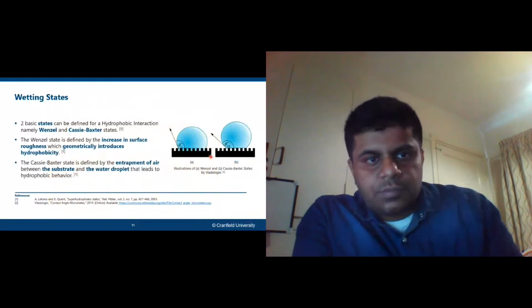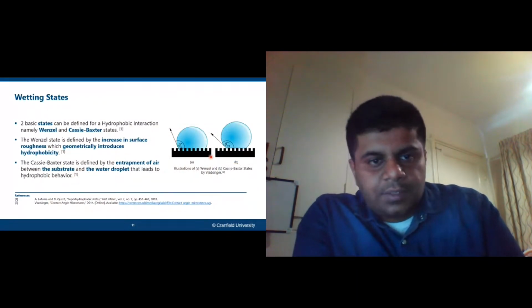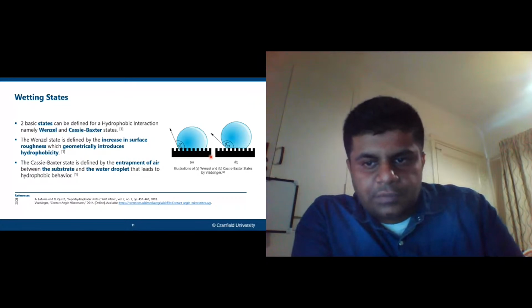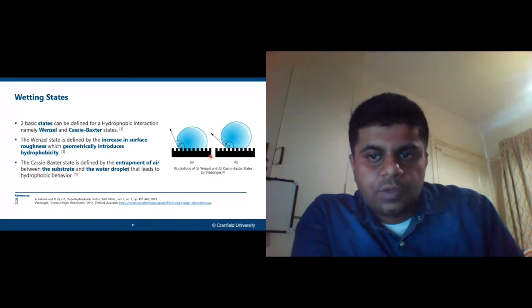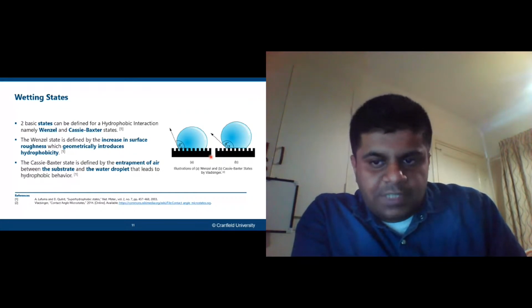So the two wetting states that we are discussing today are Wenzel and Cassie-Baxter. With regard to the Wenzel state, it's when the water droplet is fully in contact with the substrate surface down below. As you can see, the water droplet makes full intimate contact with the surface, and when you add more water or the droplet size is increased, the adherence is so strong that the droplet just grows and does not leave the substrate it was touching before, so you receive high contact angles that way.